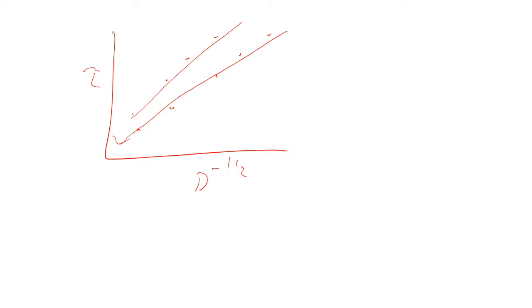And the reason for that is when you're down in that regime, if you think about when you have grains that consist of tens of atoms, almost every single one of those atoms is at a grain boundary. So the fraction of grain boundary is huge; your whole metal is basically a surface defect with tiny pockets of ordered atoms. And when you have that huge volume of grain boundaries, it's easy to activate things like grain boundary sliding or local recrystallization or grain rotation, things that you can't do when you have a big crystal with a very thin grain boundary. But that's what's meant by the inverse Hall-Petch.